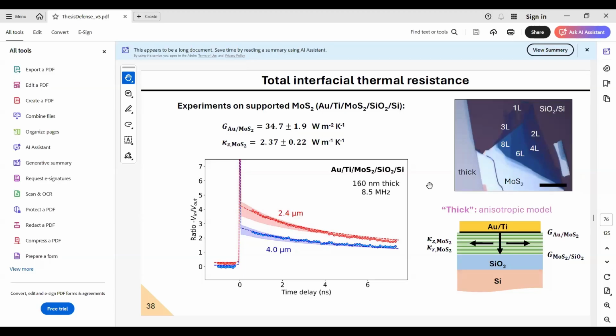Therefore, we put our 2D material on top, and you can see it is also very flat. You don't see blisters, you don't see spots or dust or whatever. Our TDTR maps also show super homogeneous thickness regions, implying that our interfaces are very conformal to a flat surface. Then growing the gold on top, it's like growing gold on a flat surface. Of course, it could be different how it grows on molybdenum disulfide or on silicon oxide. So comparing those 2 could be tricky, but still you have a flat template. So not sure we can comment much on roughness in this particular experiment. Yeah.